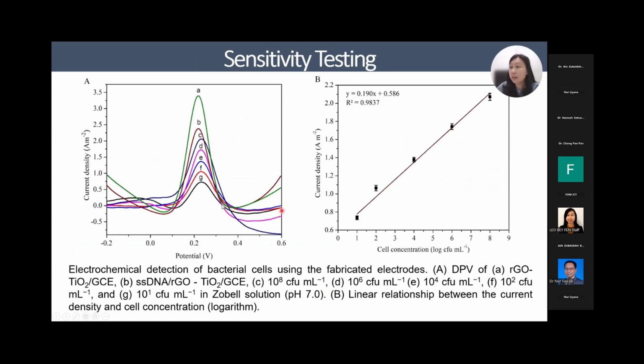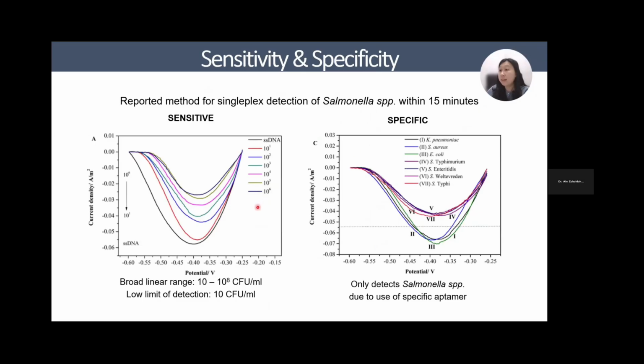Then we further continue our analysis with the sensitivity test. Here shows electrochemical detection of the bacterial cells using the fabricated electrode, with different concentrations of bacteria from 10^1 to 10^8 CFU per mL in the solutions. We plot the current density versus the different concentrations of bacteria, and you can see the linear relationship between the current density and the cell concentrations, with R squared 0.98 linearity. You can see from this graph that the detection limit can go down to 10 CFU per mL.